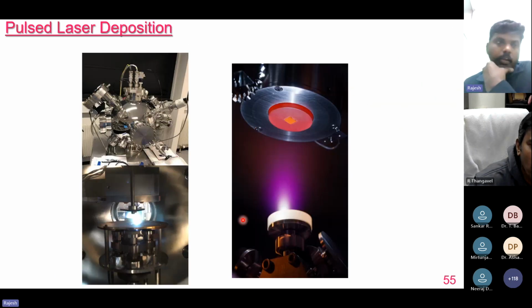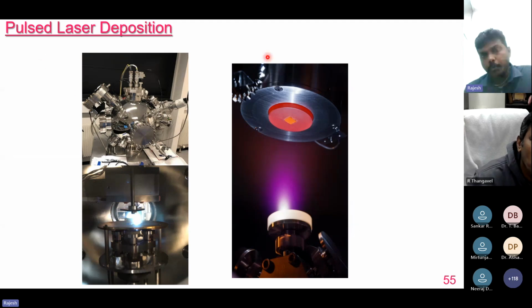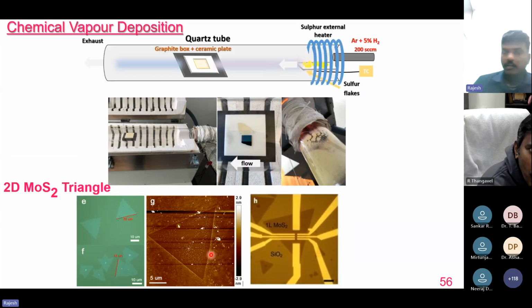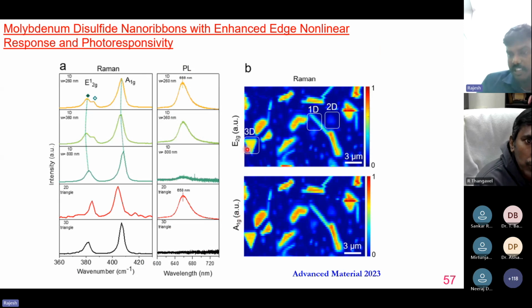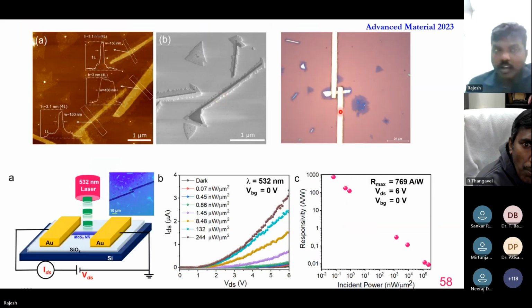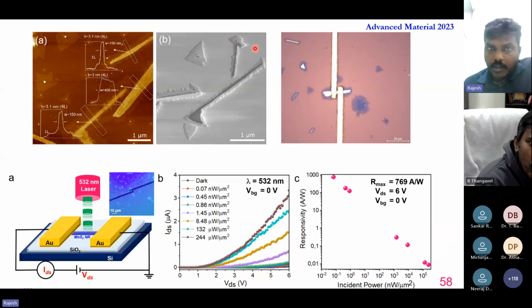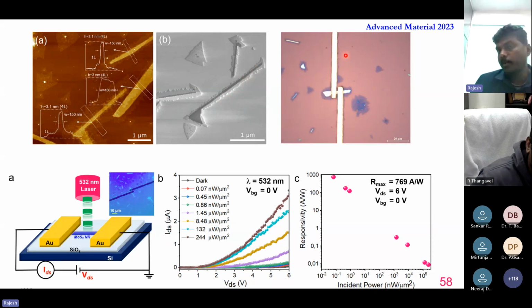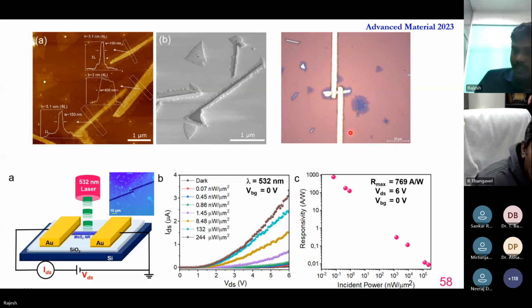We also studied quasi-MoS2 nanoribbon with the help of pulsed laser deposition and chemical vapor deposition. By using these two techniques, we are able to grow quasi-nanoribbon structures. As you can see, we obtained three kinds of structures: monolayer MoS2, then bulk MoS2, then quasi-MoS2 nanoribbon. It's a combination of one-dimensional and two-dimensional. This is a bulk one-dimensional MoS2 surrounded by monolayer two-dimensional MoS2, so we can say it is a quasi-MoS2. Again, we fabricated a photodetector on these quasi structures and demonstrated photoresponsivity, and we achieved a very high responsivity as compared to monolayer MoS2.